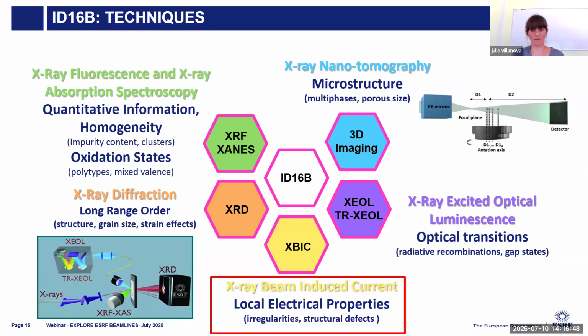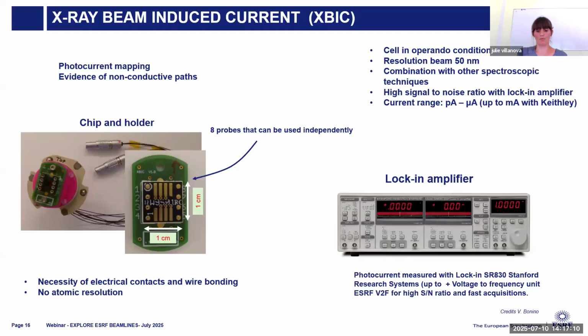So we have fluorescence, we have diffraction, but we can also adapt X-ray beam induced current. This is used in order to look at the local electrical properties in the sample, and can be coupled with the fluorescence and with XEOL measurements that I will present to you afterwards. The principle is that we will actually probe the electrons that are produced in the sample thanks to an electrical circuit. We will scan in 2D point by point in our sample and record at each point the photocurrent that is produced. Here you have a picture of the setup, where we will adapt the sample on this connection.